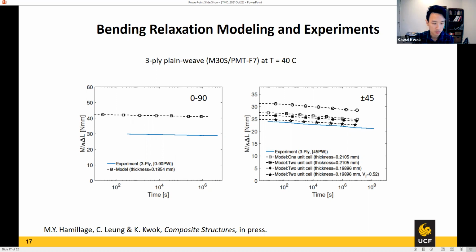There's a recent paper that talks about a neutral axis shift in carbon fibers: if you look at the tension and the compression behavior of carbon fibers, they're actually quite different, with the compression response being weaker, so less stiff. However, in our model we did not take that into account because our model is just linear elastic, so the same in tension and compression. The reason, obviously, is that the compression test on a carbon fiber is extremely hard to do, so there's not much data around. And this paper that recently came out from ETH shows that if you have a unidirectional composite and you look at the strain on both sides, the strain is actually higher on the compressive side than the tension side.